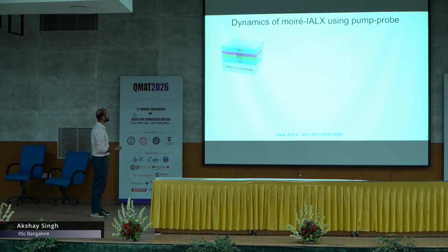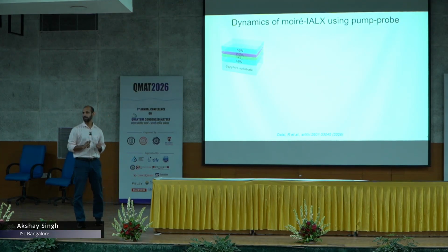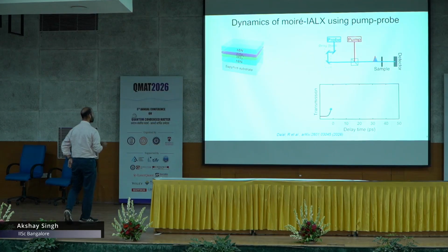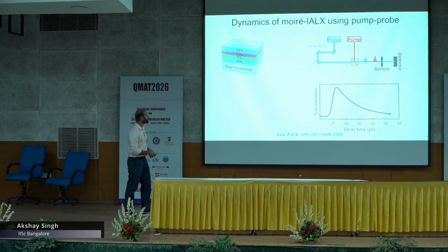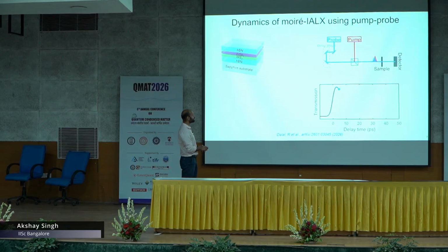So we have this hBN encapsulated WSe2/WS2 heterostructure on a sapphire substrate. Here I should mention we do measurements in transmission, because the reflectivity actually introduces a phase, so we want to get rid of that. So the measurement that we do is a pump probe measurement. Because not everybody would have looked at a pump probe measurement, I'll just walk you through it. So imagine a pump pulse, a pulse of light. It's a femtosecond or a picosecond pulse.